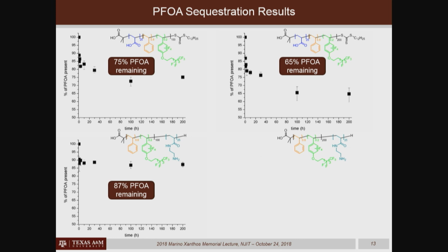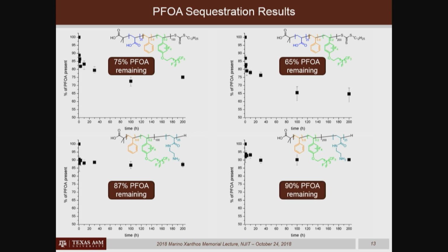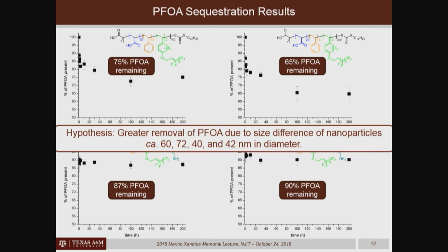Here only 13%. In this case, about 10%. And so right now, we have not published these results yet because we're still trying to figure out what are the parameters that lead to the ability of these particles to capture perfluorooctanoic acid. Our current hypothesis is that because these two particles were larger in dimensions, 60 and 72 nanometers in diameter respectively, versus 40 and 42 nanometers in diameter here, that may have impacted the ability to package the perfluorooctanoic acid.